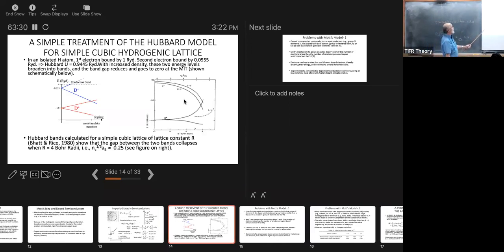The electron that's bound to the ion is at -1 Rydberg in this unit. The second electron, which isn't there right now, is only bound by 0.055 Rydberg. This is very well known, in fact, 0.0555 is known to 4 digits. It's one case where the theorists can do better than the experimentalists, because it's just a 2-electron problem. You can do a 180 variational parameter calculation and get 5-digit accuracy without any difficulty.